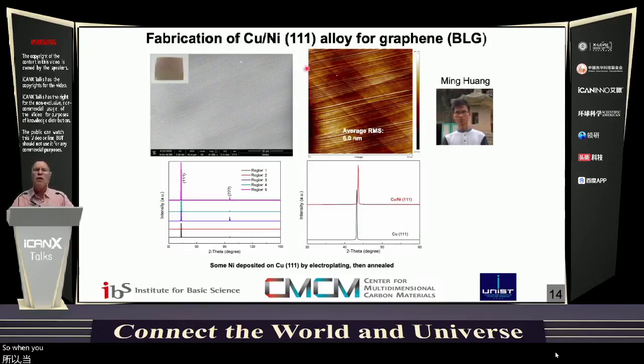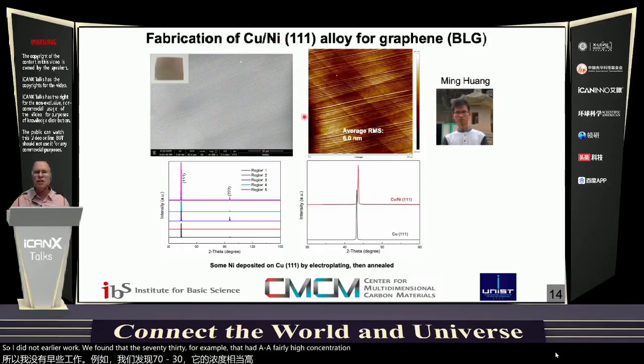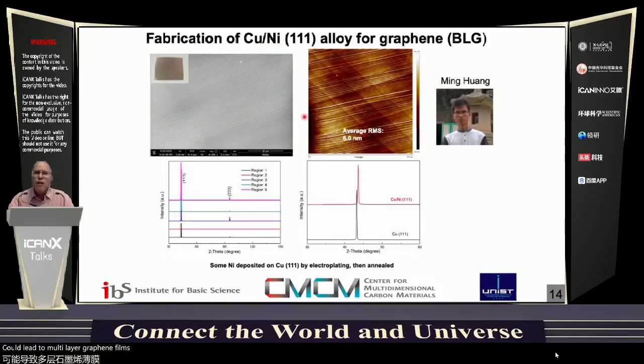So when you hear about 90-10 and 80-20 and 70-30 copper nickel foils, they have more than copper and nickel in them, but they're excellent for anti-corrosion. So indeed, in the earlier work, we found that the 70-30, for example, that had a fairly high concentration of nickel could lead to multi-layer graphene films. And this was some very nice work in my group at UT Austin by Shen Chen and Yaping Wu and several different papers along with our colleagues and co-authors.